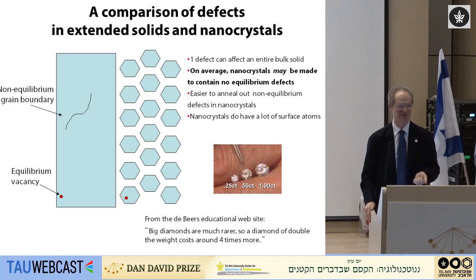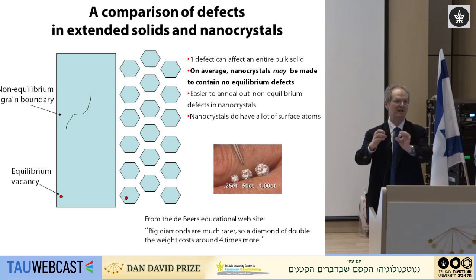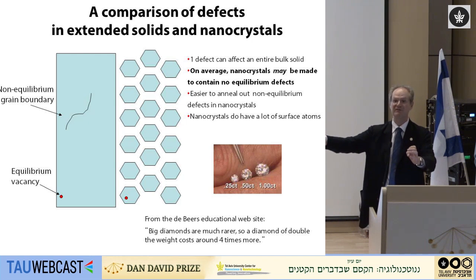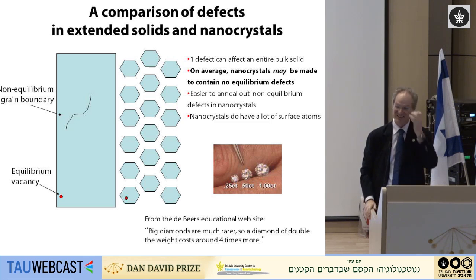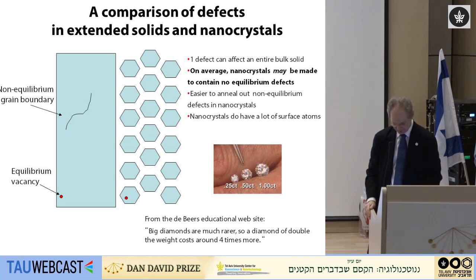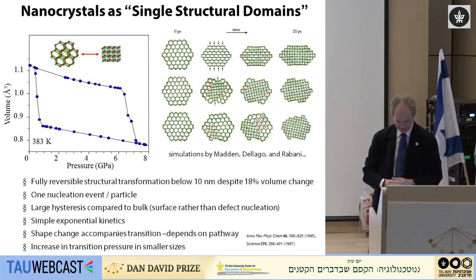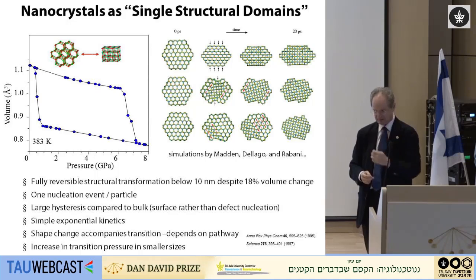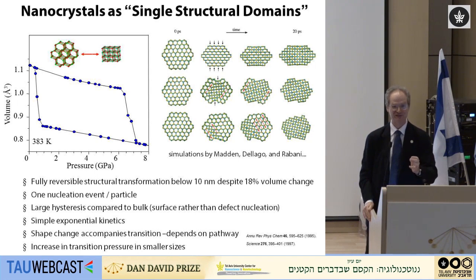And because the crystals are so small, the equilibrium defects will only be one defect in very, very large number of tiny crystals. I can have a huge number of tiny crystals, and at equilibrium there will only be maybe one of those crystals has a defect inside of it. So as a consequence, one of the really beautiful things about nanoscience is that it's possible to make very perfect crystals, and that these crystals are very robust. Now, that doesn't mean you will always make perfect crystals. It's possible even to make a nanocrystal very badly. But if you pay attention to the conditions, they favor the formation of a good crystal.